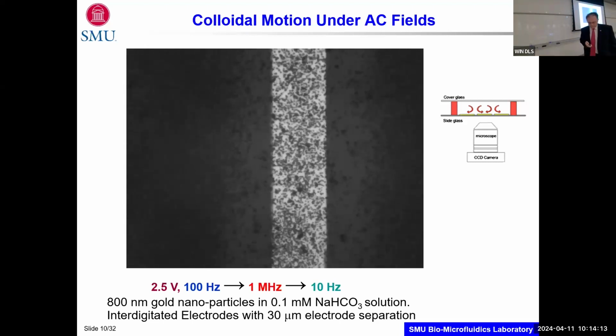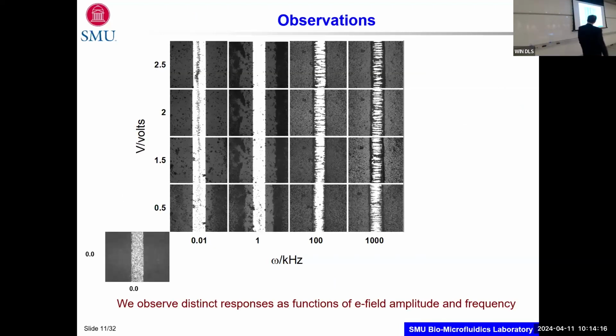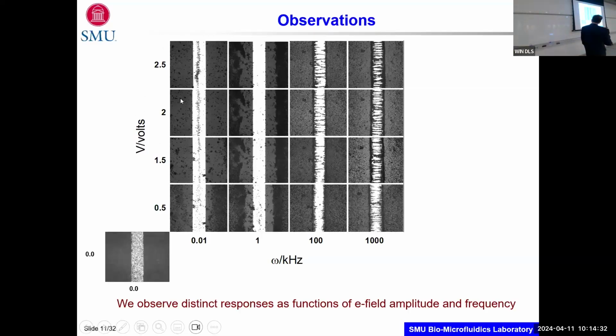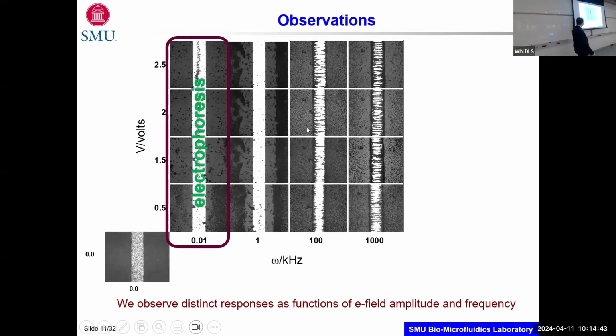So we did these experiments systematically at different voltages and frequencies, and we also saw some consistent cases. For example, frequency-based consistency. Of course, the value of the voltage is too low here, but you saw the vibration of the particles, and then you saw a case where the particles were leaving the gap and going to the sides of the electrodes, and particle chaining. So indeed, the first thing that we have seen is known as electrophoresis or electroacoustics of the particles. Those are the particles vibrating.